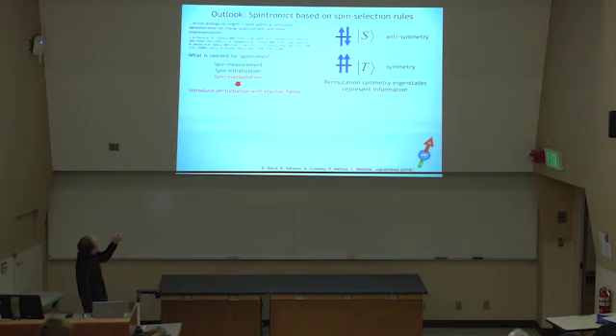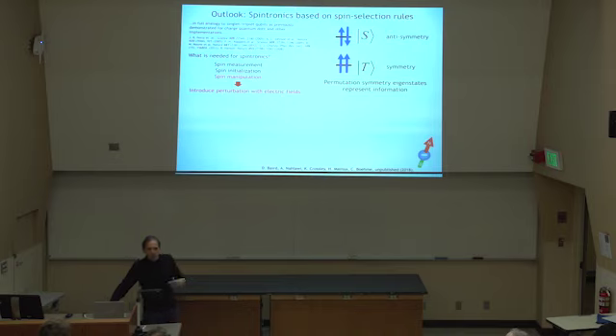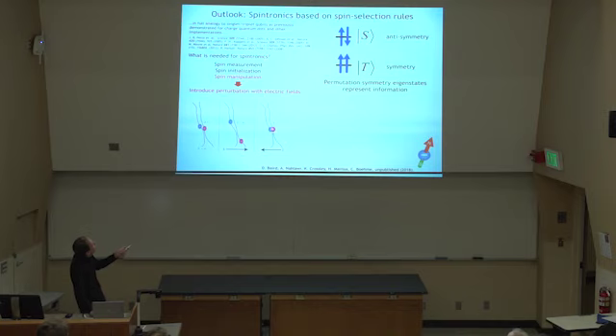So we want to manipulate spins, obviously not by spin-orbit coupling, because that's very weak. So Rashba interaction or Dresselhaus based spin manipulation is not really feasible. But maybe electric field manipulation, because in these floppy materials, we can manipulate distances through electric fields. And does this work? Do we have first data that supports this hypothesis? I mean, that's another cartoon. And that tells us that electrons are blue and holes are red, and not much more.